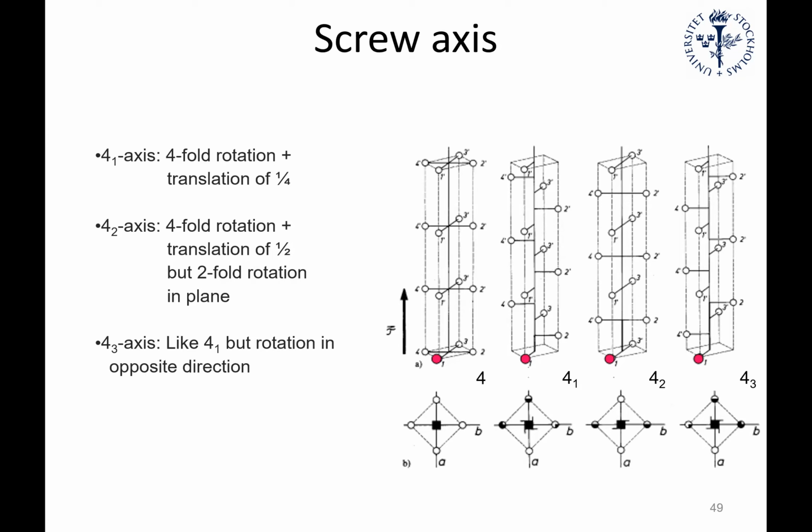4-2, what is happening here? So with 4-2, this 2 in subscript, I like to imagine it as you have twofold rotational symmetry now. So you see along this screw axis, there's an equivalent point related by a twofold rotational symmetry, this position here. But to go from these 2 points to the next 2 points, we still have to rotate it 90 degrees. That's why it's fourfold.